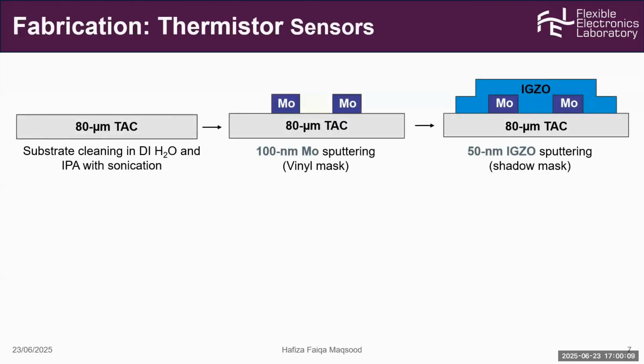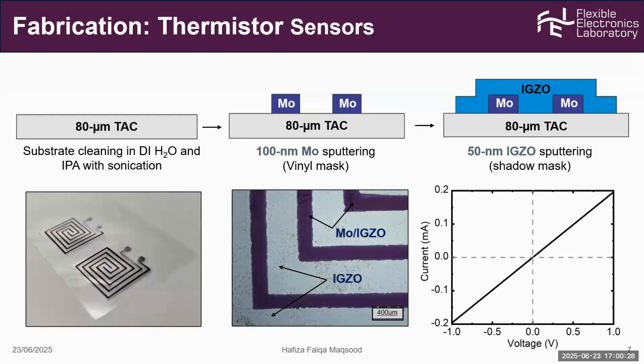For the fabrication of the thermistor sensor, again we start with 80 micrometer TAC substrates, and we sputtered 100 nanometer molybdenum as electrodes, and then we sputtered 50 nanometer IGZO due to its semiconducting and temperature sensing properties. The schematic shows a simple layout of IGZO and the molybdenum contact, and the micrograph shows a continuous film coverage without any breaking. We again did IV measurements, and the result is linear and symmetric, and the value of the resistance is around 5 kilo-ohm.